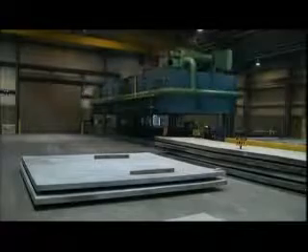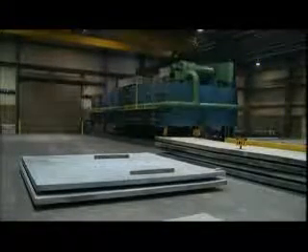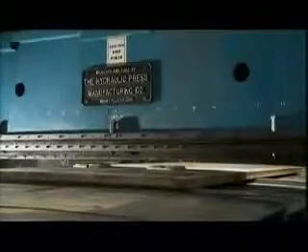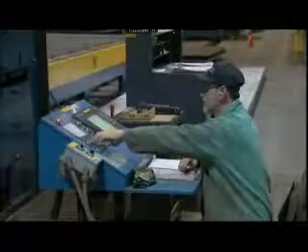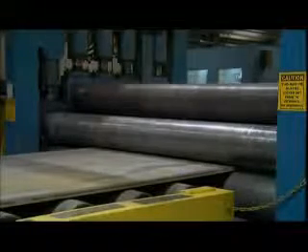Not surprisingly, the power of the explosion can cause significant deformation to the newly formed clad. Therefore, upon its return to DMC's central processing facility, the clad undergoes a final series of corrections. These include heating the clad in an oven that causes the metals to soften slightly. This relieves stress from the blunt force of the explosion's impact. Any bowing or misshapen curves are flattened out by either a 3 million pound press or, for thinner clad, by a series of rollers known as levelers.